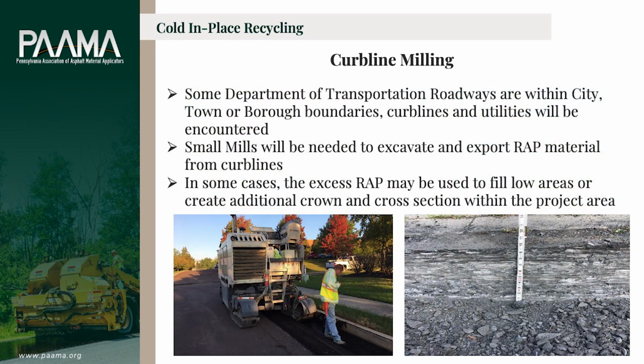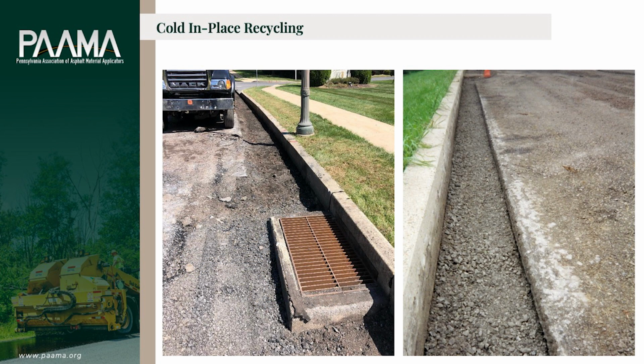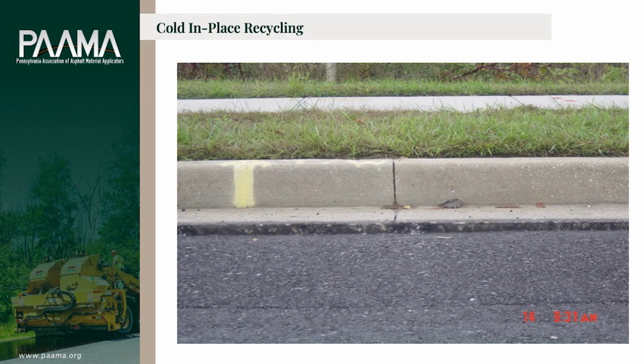Curb reveal. So when we're working with a borough, we need to cut out the curb lines. We don't want that 50-ton recycling machine pushing against any curb faces, scratching them up or destroying them. So we edge out along the curbs, around all the utilities, whether it's a catch basin or a valve box or a manhole, and we cut all that material out and export it away. In a situation like this, where we have a roll gutter pan, we're leaving a 1.5 inch wedge there because we know there's 1.5 inch of 9.5 millimeter, which is going to be the wearing surface on top of the recycled base. So we're always looking at, well, what's the final wearing going to be on this particular roadway?